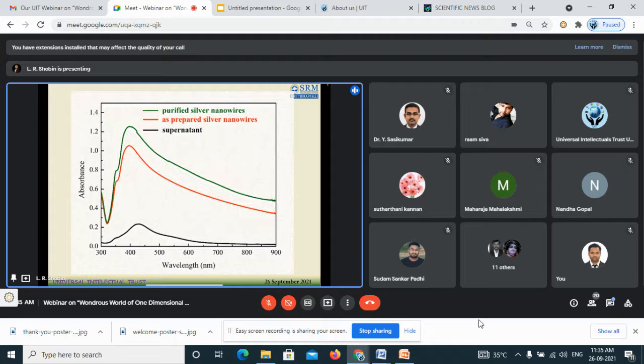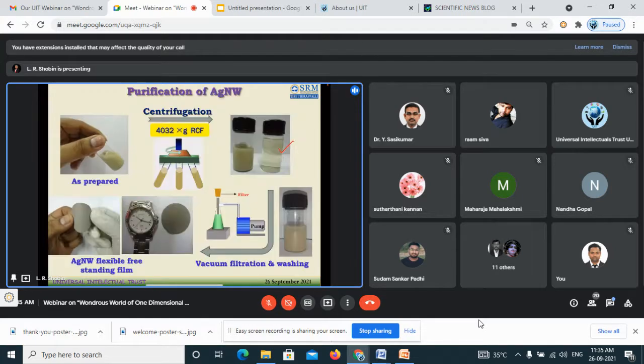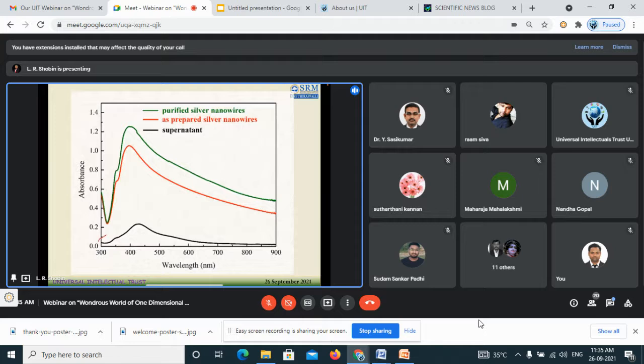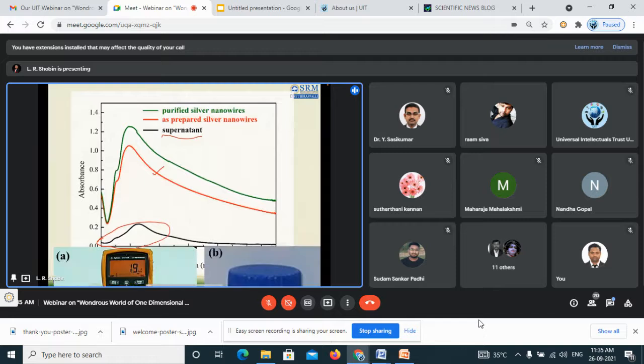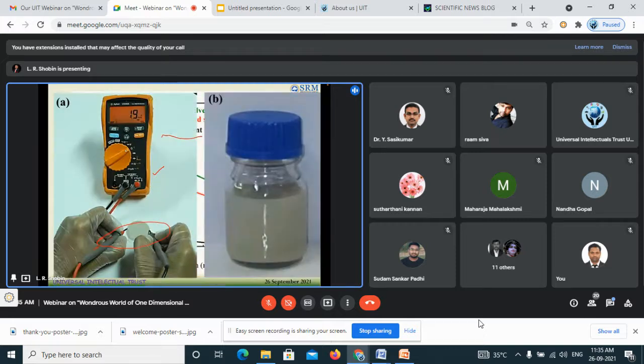Yes, it is good, because if you take the supernatant, say for example, this solution I am talking about, which will have only the particles. If you see the as-prepared substance here, it will have particles, this red color shows the particles, as well as wires. But this supernatant will only have the particles. So it shows that you are able to remove the particles from the system.